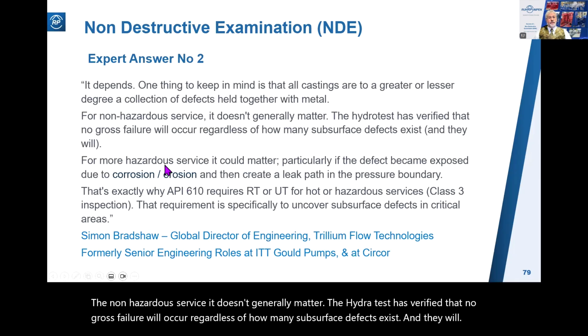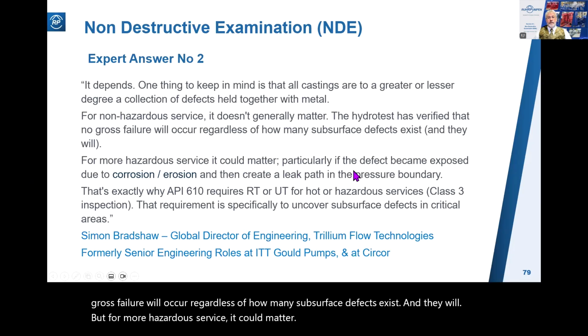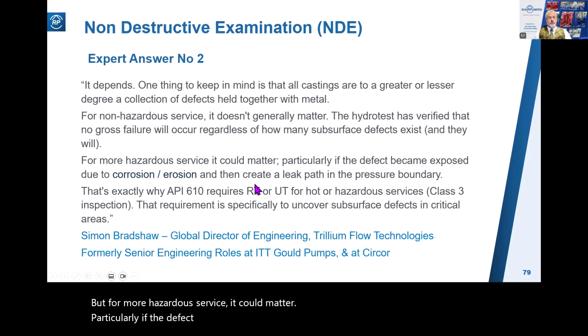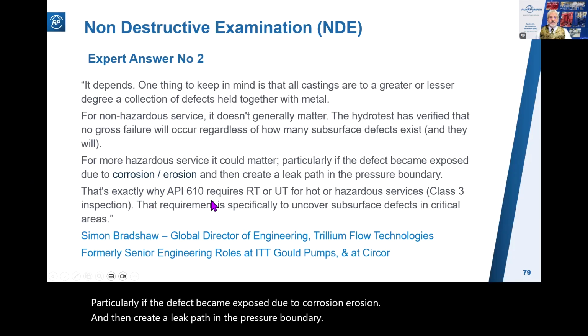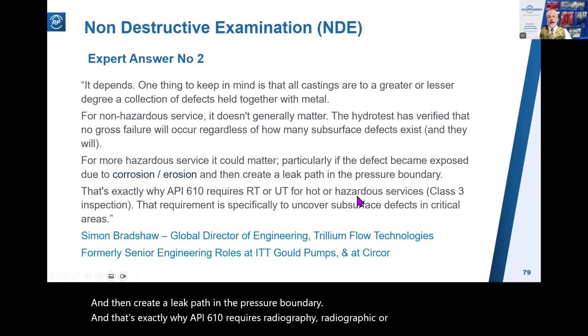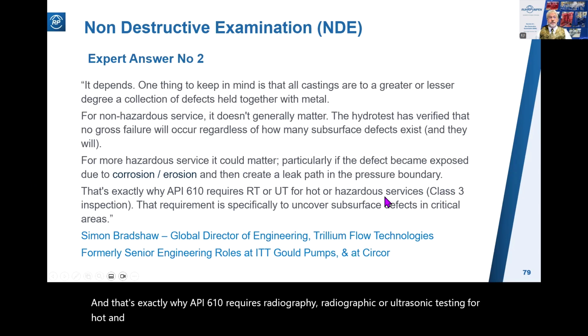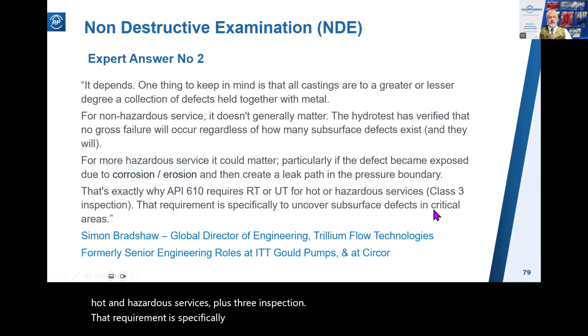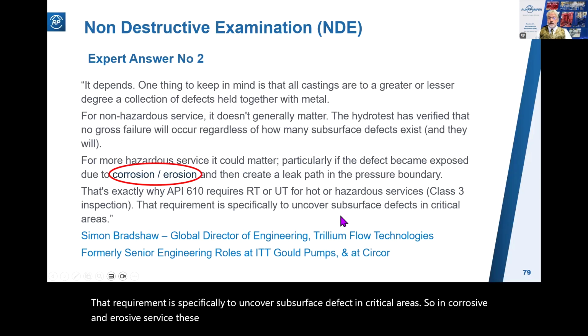But for more hazardous service, it could matter, particularly if the defect became exposed due to corrosion, erosion, and then create a leak path in the pressure boundary. And that's exactly why API 610 requires radiographic or ultrasonic testing for hot and hazardous services, class 3 inspection. That requirement is specifically to uncover subsurface defects in critical areas. So in corrosive and erosive service, these subsurface defects could become surface defects. So there you have the answer.